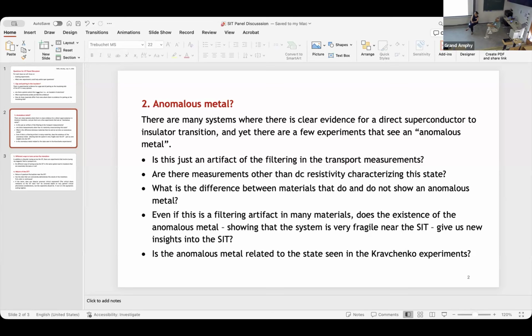I think people by now know how to filter the cryostat. Some samples have been measured in several groups. I've sent samples to Christophe. I've sent samples to Danny Shahar when he was still in the field, and all measured the same thing. It was induced by thickness. It was measured in our case in niobium silicon on a single sample by annealing the same sample. Recently, we did some pressure experiments with Avia showing that in indium oxide we have such kind of anomalous metals. So yeah, I think we should understand what's... I agree with the questions. I'm not sure I have a clear answer to those, but yes.